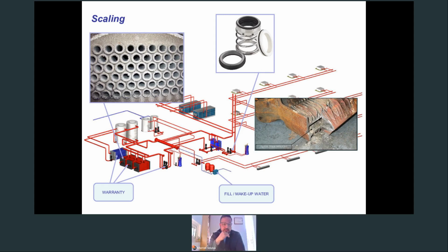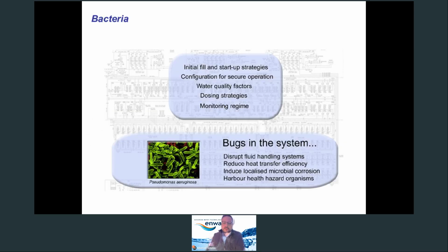So the direct impact of scaling is obviously scaling on hot surfaces, and it also impacts components such as pump seals and O-rings, which are some of the first components to experience problems. The indirect cause of scaling is large particle generation, which again begins to clog up surfaces and heat transfer components such as plate heat exchangers. And there you see on the screen a picture, for example, of a cast iron boiler section where the insulation effect causes hot spots and failures, eventually leading to leaks and excessive top up also. So it's important to have that strategy also, which will advise on what the initial fill water should be.